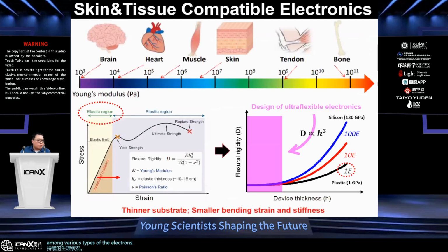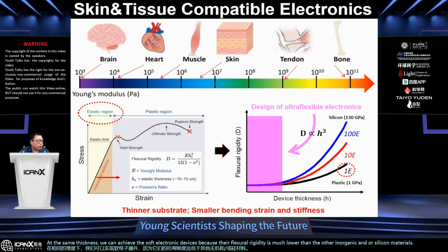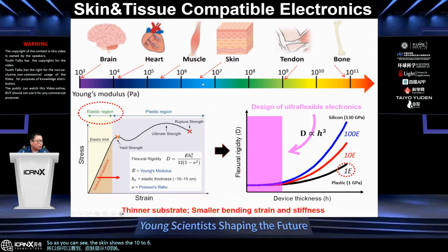Among various types of electronic devices, organic-based electronic devices are one of the good candidates for futuristic human-friendly sensors, because the Young's modulus of organic materials is 100 times lower than that of silicon or inorganic materials. At the same thickness, we can achieve soft electronic devices because their flexural rigidity is much lower than other inorganic and/or silicon materials. Also, by reducing the total thickness of the devices down to the few-micrometer scale, we can achieve highly soft devices that can be applied as skin and/or tissue compatible sensors because of the similar mechanical properties between the skin and the devices. As you can see, the skin shows about 10^6 Pascal of mechanical softness, which is Young's modulus. But by designing the total thickness below the micro scale, we can have much softer devices.